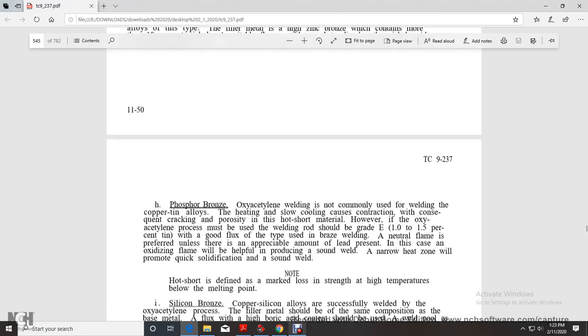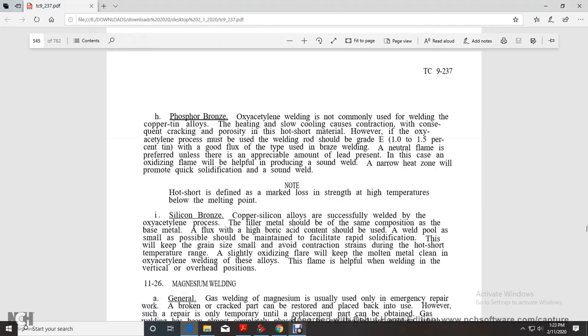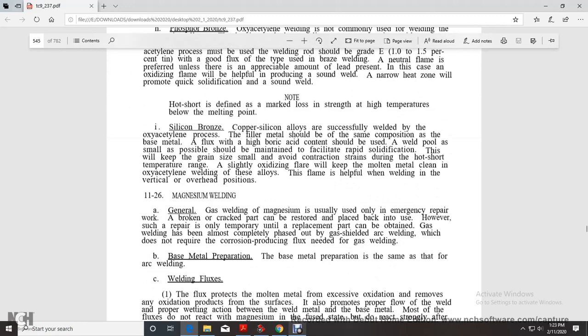Phosphorus bronze: oxyacetylene welding is not commonly used for welding of copper tin alloy. A heating and slow cooling cause contraction and consequently cracking and porosity, with a hot short material. However, the oxyacetylene must be used. The welding rod should be grade E with 1.0 to 1.5 percent tin. The good flux of the brazing type is used. Welding with a neutral flame is preferred unless an appreciable amount of lead is present. In this case, the oxidizing flame is helpful in producing a sound weld. A narrow heat zone promotes the quick solidification of a sound weld. Hot-short is defined as a marked loss in strength at high temperatures below the melting point.